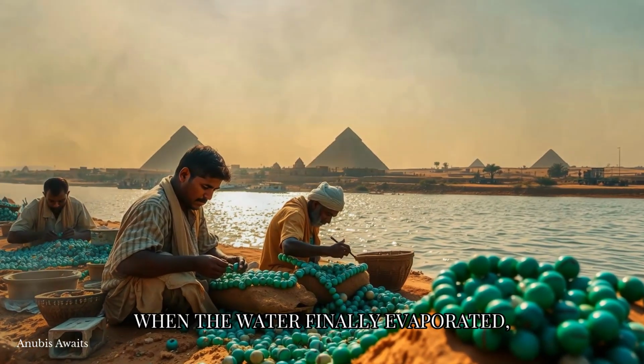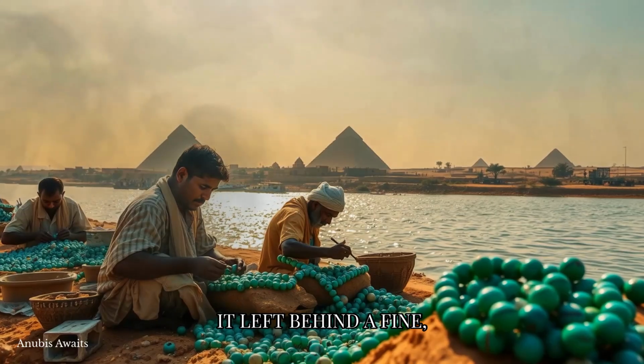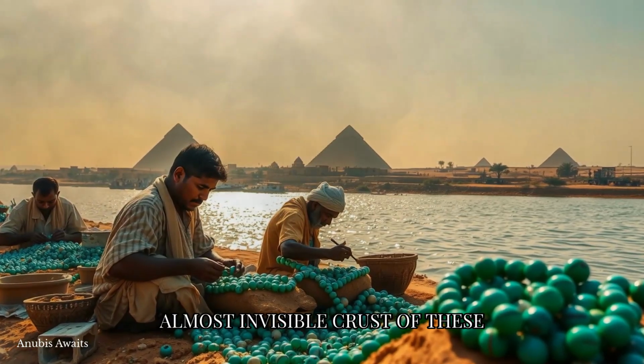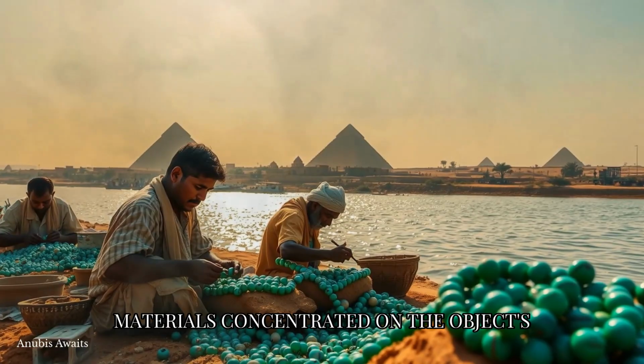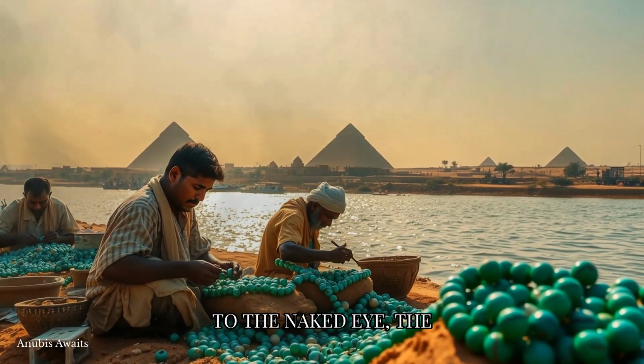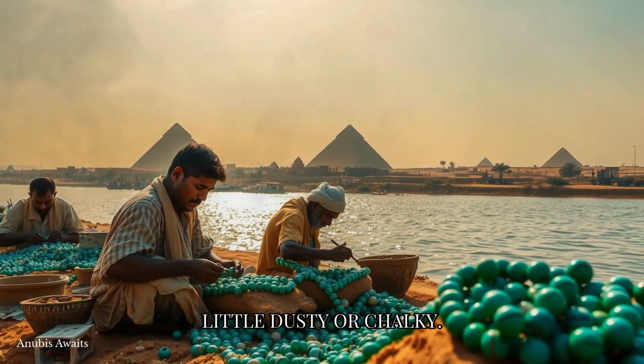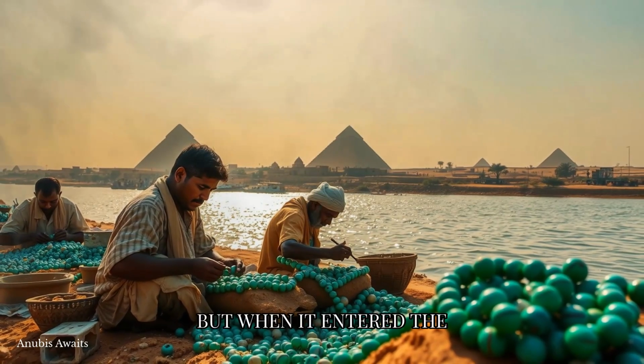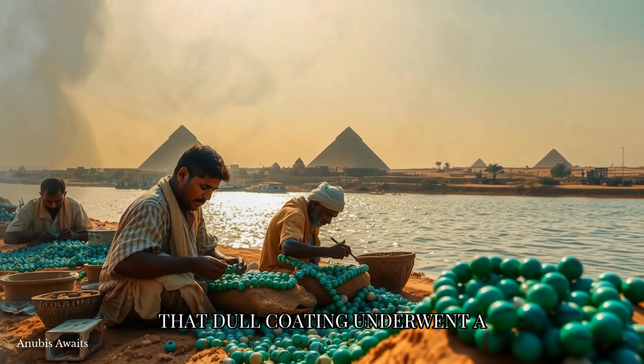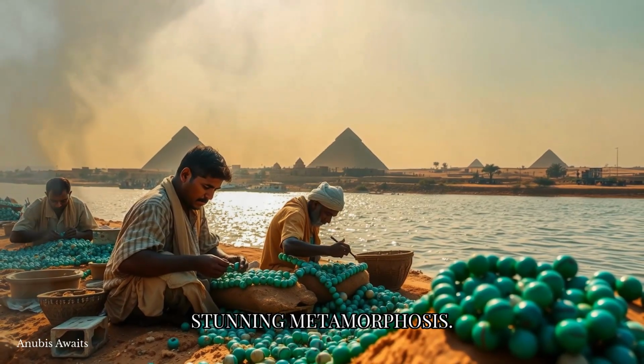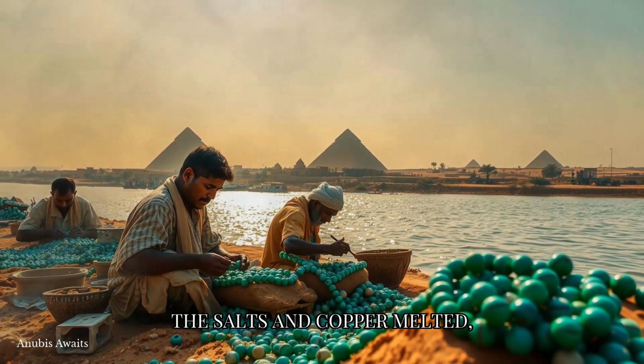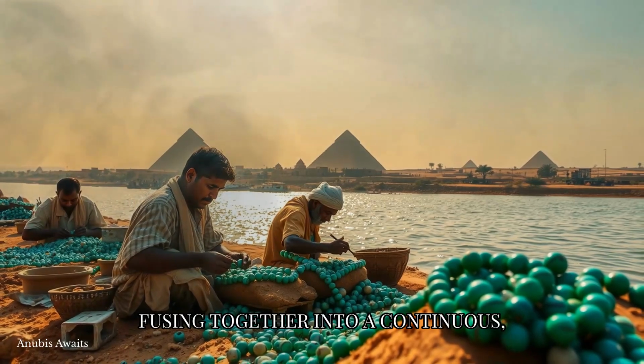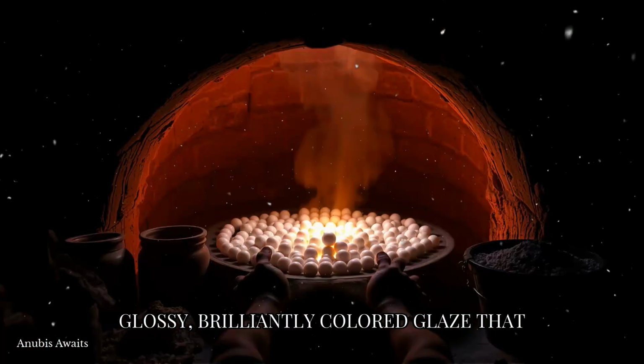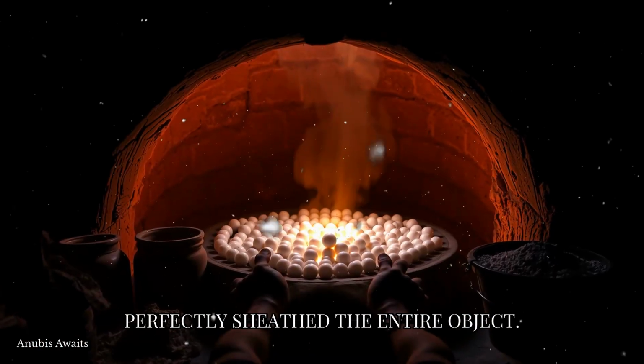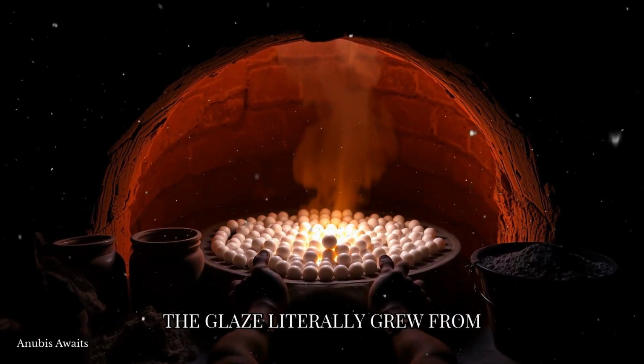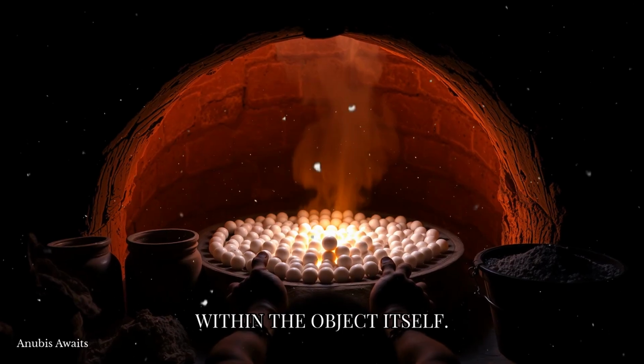When the water finally evaporated, it left behind a fine, almost invisible crust of these materials concentrated on the object's skin. To the naked eye, the dried bead just looked a little dusty or chalky. But when it entered the intense heat of the kiln, that dull coating underwent a stunning metamorphosis. The salts and copper melted, fusing together into a continuous, glossy, brilliantly colored glaze that perfectly sheathed the entire object. The glaze literally grew from within the object itself.